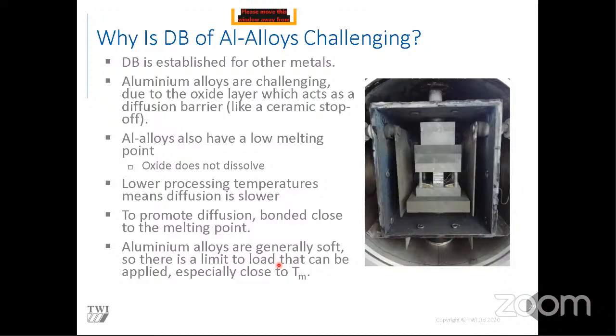But there are more issues with that. Because the actual temperatures for diffusion bonding aluminium versus titanium are lower, titanium diffusion bonds somewhere between 800 to 1,000 degrees Celsius depending on the grade, whereas aluminium is about half that, between 500 to 600, depending on your grade. So diffusion bonding is a diffusional process, and the biggest driver for diffusion is temperature. If you're bonding at a lower temperature, you're getting less diffusion. So then to promote diffusion between the parts, we actually increase the temperature to much closer to the melting point, so you're talking at 90% of the melting point rather than 60 to 80.